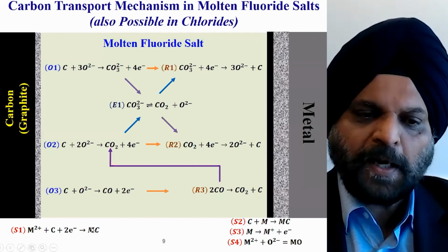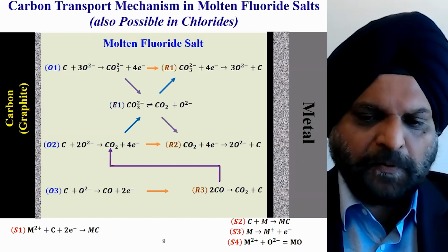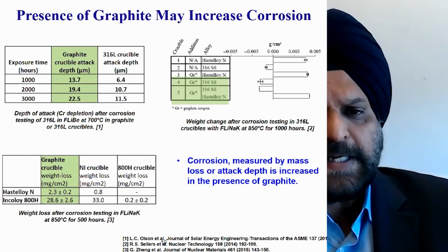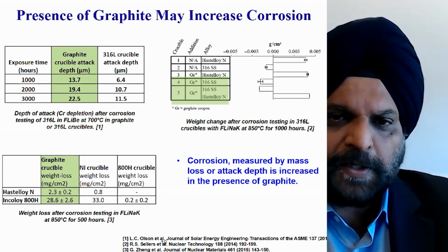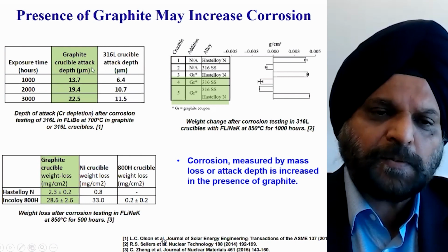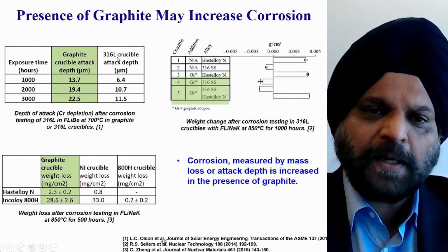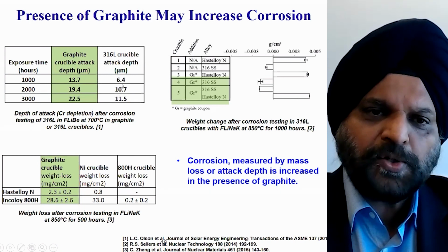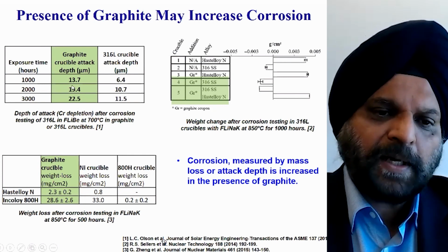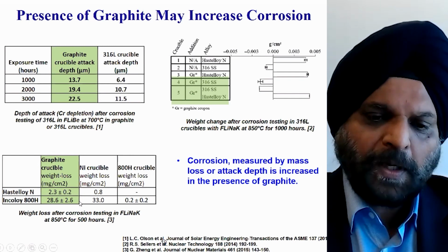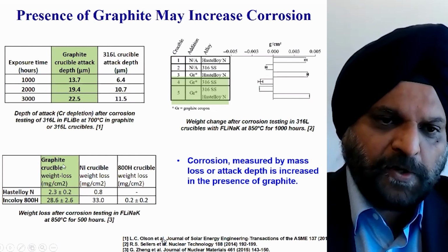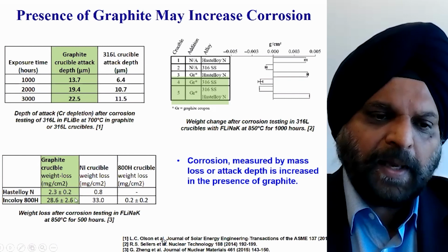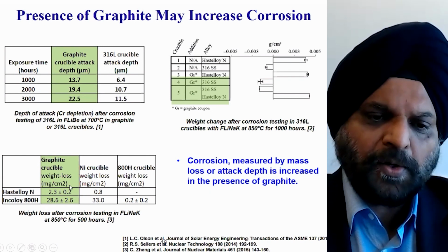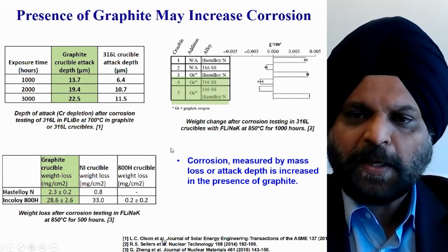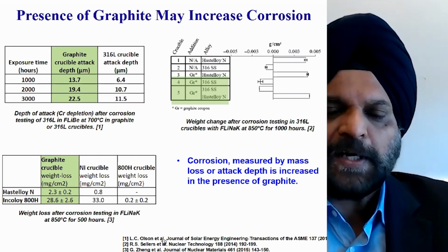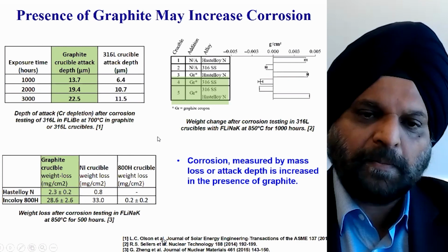And of course, you can form metal carbide on graphite because of the corrosion reaction. Work at the University of Wisconsin has consistently shown, and our work has also corroborated the same results, that if you do tests in a graphite crucible, in this case it's a 316 crucible versus a graphite crucible, you can see corrosion rates given in terms of depth of attack, they are much deeper in graphite. Again, this is work by Zheng, again, from University of Wisconsin, nickel crucible versus graphite crucible, Hastelloy versus Incoloy 800H. Corrosion rates typically are higher for graphite. So corrosion can be increased if there is any graphite available at or near the metal surface.